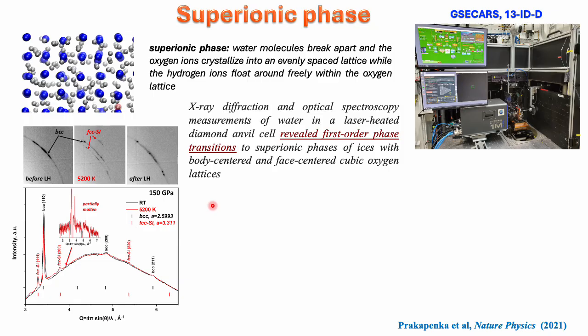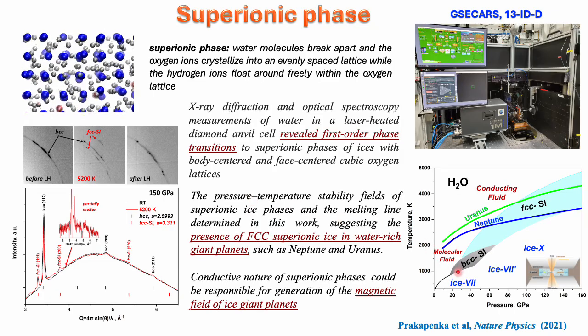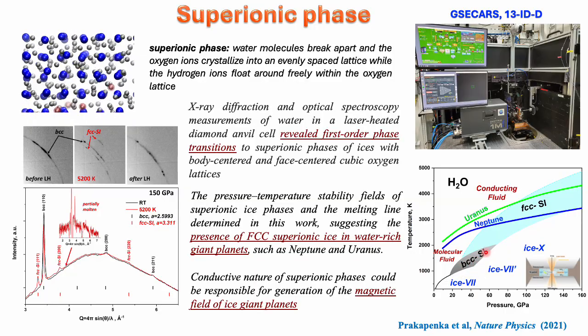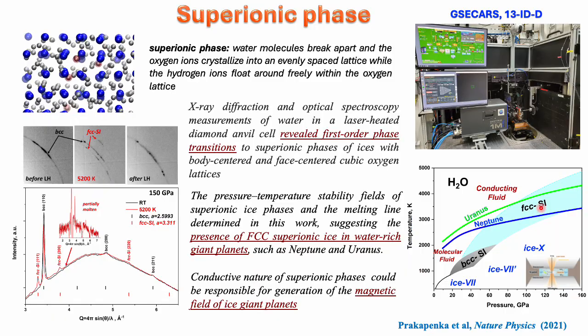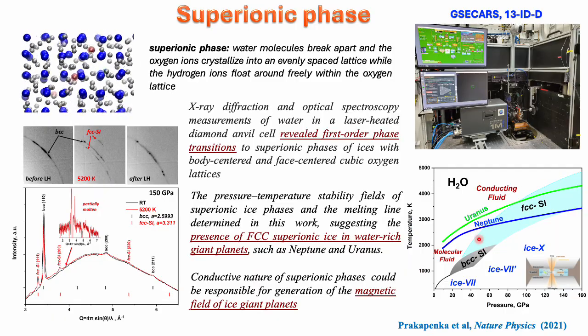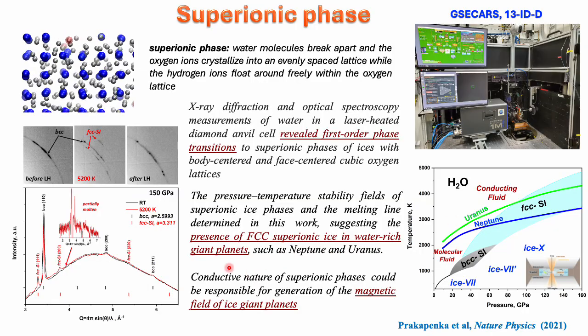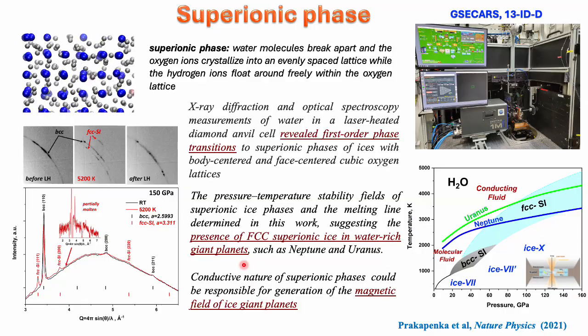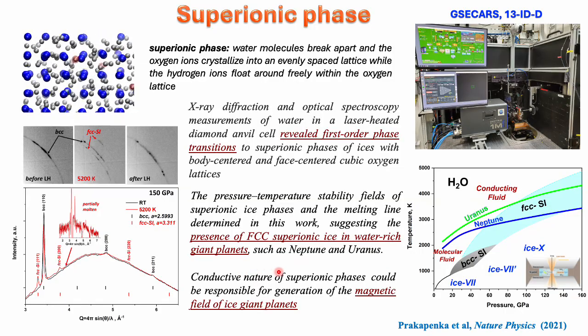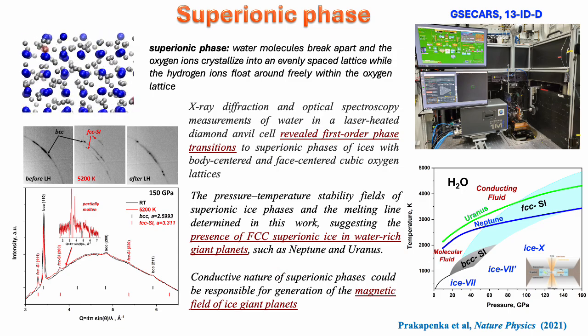We were able to heat the sample at up to 150 GPa and found a phase transition. As you can see, ice VII or ice X at these conditions has a very simple cubic BCC structure, but when we heat it to above 3000 degrees, we can see a transformation to an FCC phase. So it's a first order phase transition, and collecting multiple data sets, we were able to find that ice VII transforms to BCC superionic ice, and that actually has a phase transition to an FCC superionic phase, and it actually crosses the Uranus and Neptune adiabats. That may bring us to the conclusion that the conductive nature of the superionic phase could be responsible for generation of the magnetic field of the ice giant planets.